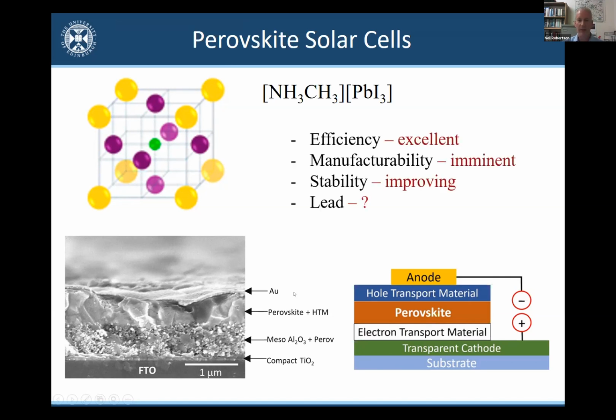So what's the big deal with lead halide perovskite solar cells? Well, as I said before, they have excellent efficiency comparable with crystalline silicon. However, because this material is soluble and can be dissolved in solution, they can be manufactured by printing processes rather than the high energy, high cost methodologies used for crystalline silicon. So they have the potential to reach ultra low costs. Manufacturability, imminent. I'll say more about that later.